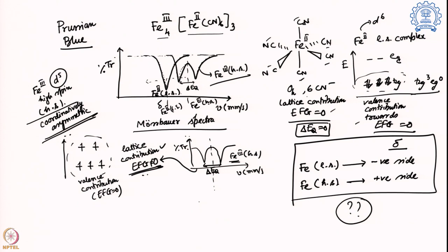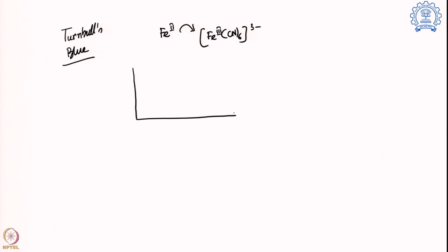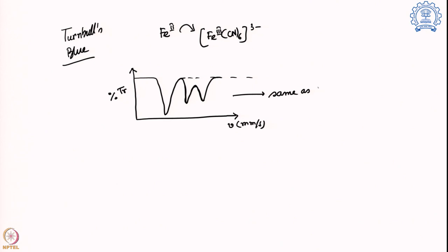And that clearly says that yes, I have two different iron centers, this is the iron 2 and this is the iron 3. Now we look into the Turnbull's blue. In the Turnbull's blue, if you remember, we put iron 2 from outside into a solution of iron 3 CN6 3 minus, and then we try to find out what will be the oxidation state of this system. So then we recorded the Mössbauer spectra of this Turnbull's blue, and what we see is the following: a large peak like this and a signal like this, which is practically the same as Prussian blue.